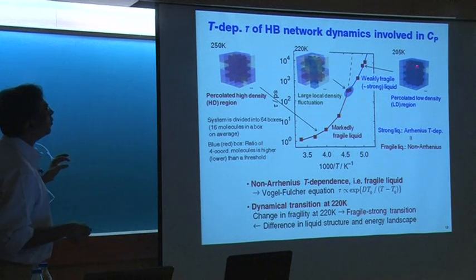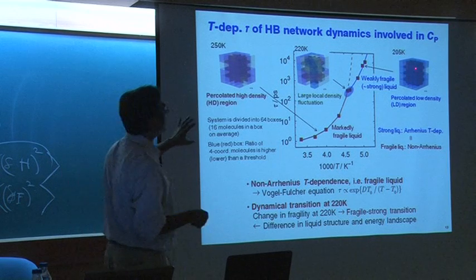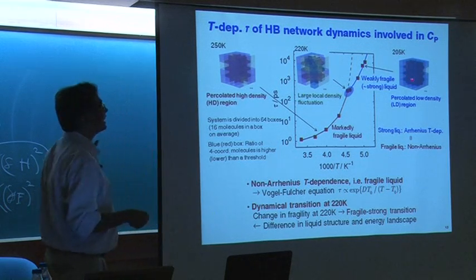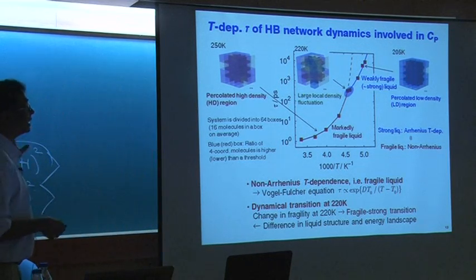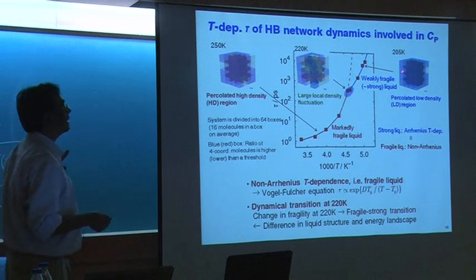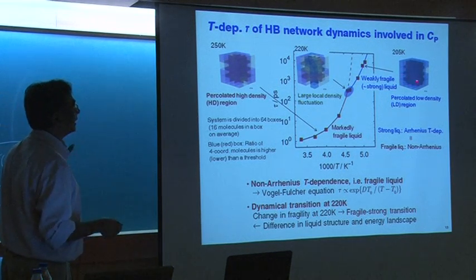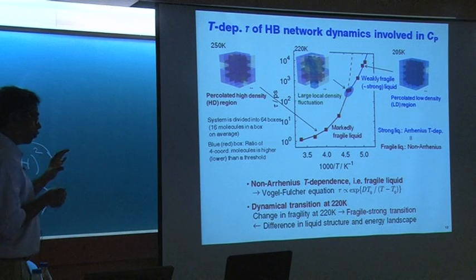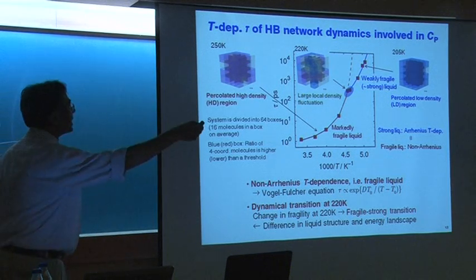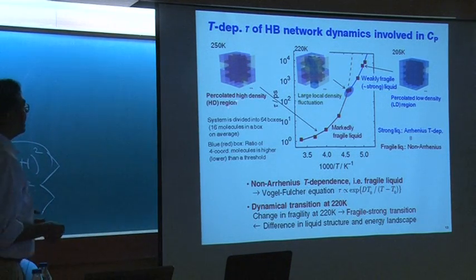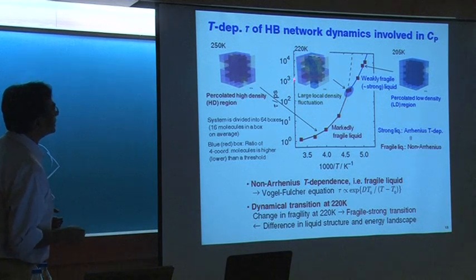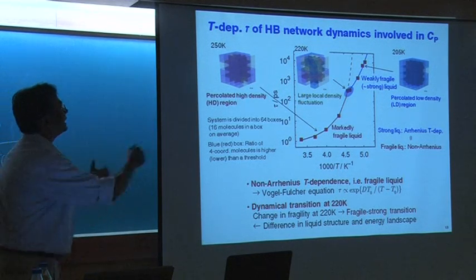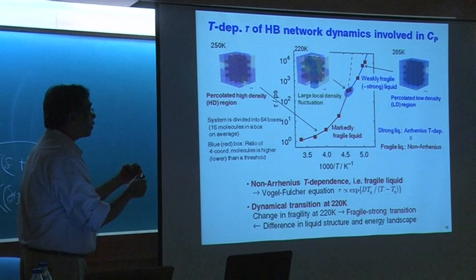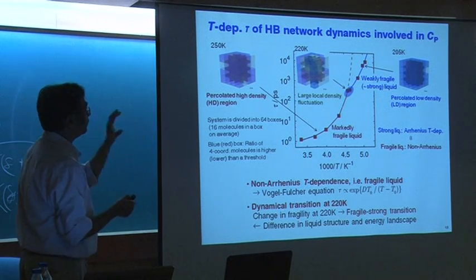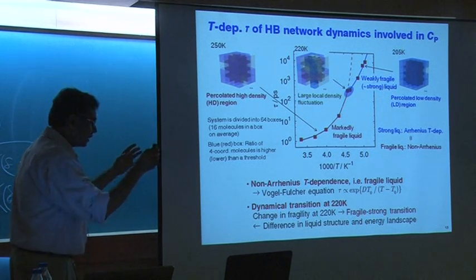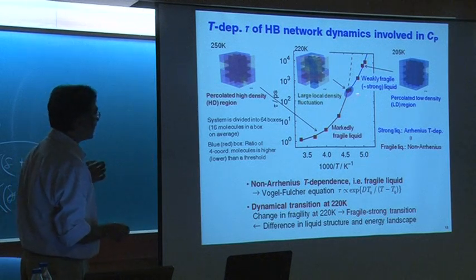Then if you go lower, it's really becoming very quiet and everything is ice-like. Here it is not crystalline ice. It becomes amorphous ice-like. There is a lot of disorder, and I will talk of that disorder. There is a local tetrahedrality, but that does not propagate like it does in ice. But these beautiful fluctuations between low density and high density continue, not at a local scale, but at a coarse-grained scale, where 2-3 nearest neighbor levels are responsible for this.